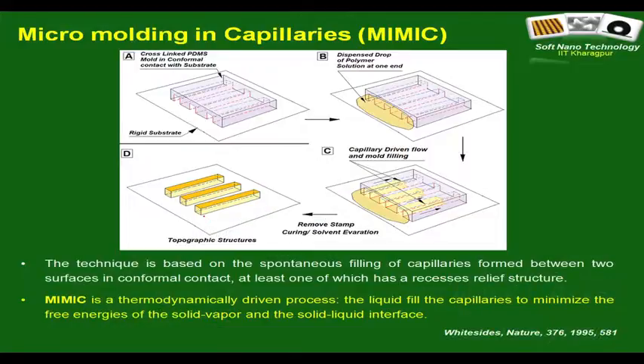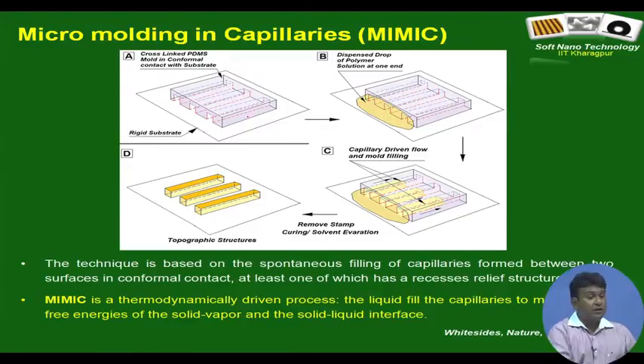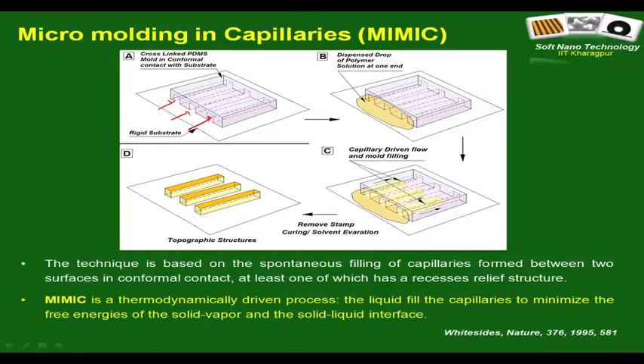In MIMIC, you do not start off with a film. You simply take a stamp created by replica molding. So, this is now flexible, and since it is flexible, you simply bring it in conformal contact with the substrate. If you have a grating pattern stamp, on one of these sides it actually makes zillions of micro channels. I have limitations, and therefore what I have shown is only a few of these structures, but you can imagine that if the periodicity of these patterns is let us say 1 micron, and your stamp dimension is let us say 1 centimeter, how many of these channels you make.